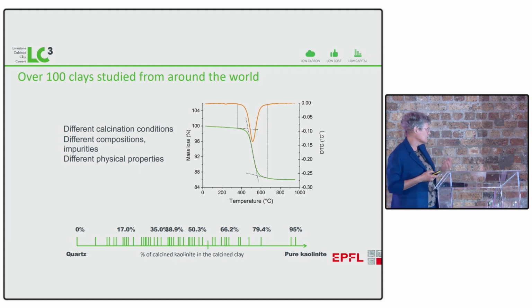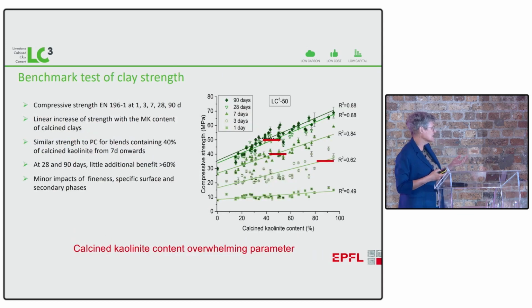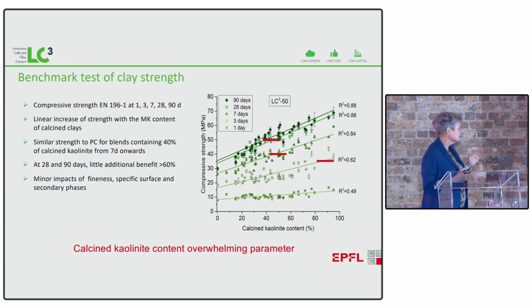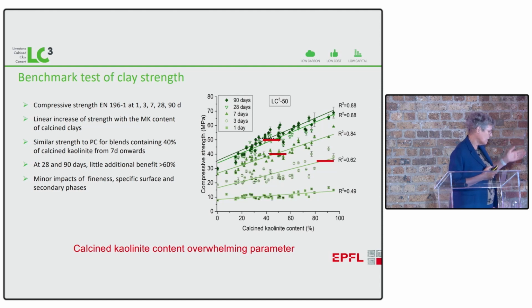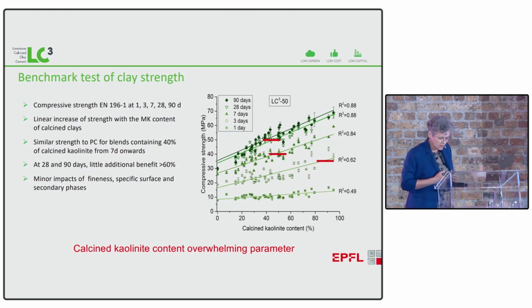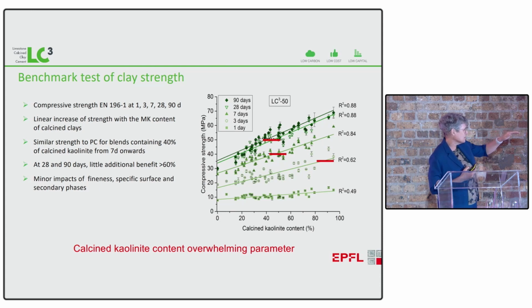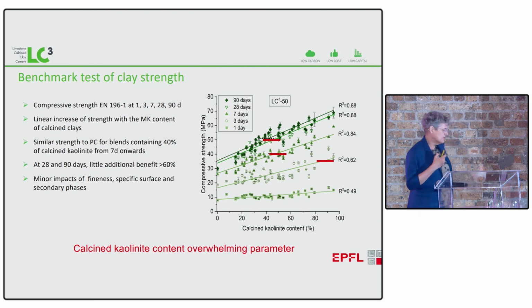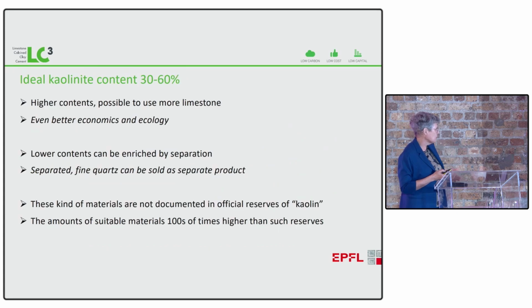And we've now studied well over 100 clays from all around the world. You can easily measure the kaolin content by looking at the loss on ignition, and we see that the strength correlates pretty well with the kaolin content. In fact, if you look at the top curve for 90 days, you see that it's not completely linear. It kind of plateaus out above about 60%. So you get very little extra benefit for going above 60% kaolin. And those red lines are the strength of the reference plain Portland cement. So you can see at 28 days you only need roughly 30 to 40% kaolin to match the strength of your reference Portland cement. So the ideal kaolin content is in this range, 30 to 60.